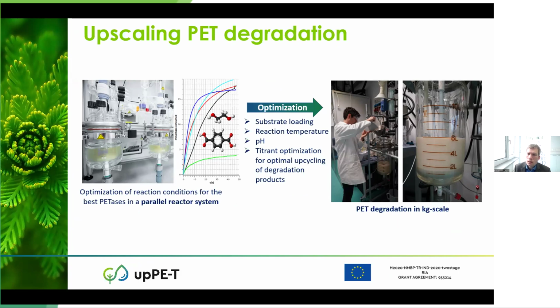There we tested different substrate loadings, reaction temperatures, also pH values, and also optimized the titrant and other conditions, in order to further optimize the conditions for further upcycling and the subsequent fermentation approach. Finally, we degraded the PET in a kilogram scale using 200 grams of PET per liter as substrate loading.